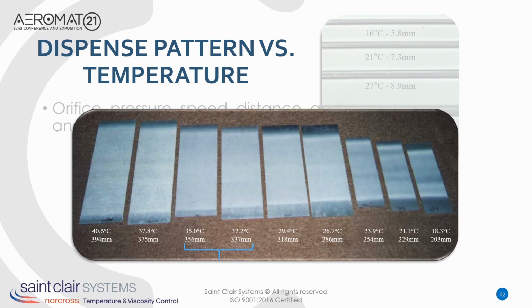In the 30 to 35 degrees C range, the coating is smooth from edge to edge. This is the optimal operating temperature for this particular process. Below 30 degrees C, when the viscosity is increasing, we see heavy edges beginning to appear, which are often associated with striping on the finished part. And as we moved into the 25 degrees C range and below, we see the combination of very uneven coating surrounded by heavy edges, which makes it very difficult to get a smooth, even coating on the finished part. And without a smooth, even coating, both performance and appearance will be compromised.